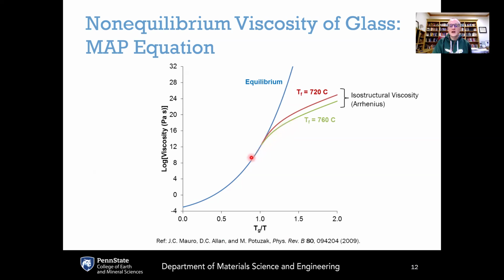You can see how the curvature here is changing gradually as the supercooled liquid departs from the blue line. It goes through this curved region, through this glass transition region, and then gradually freezes into this straight line behavior where the scaling is Arrhenius. And only at that point is the viscosity strictly isostructural. Now, depending upon how fast or how slowly you cool the supercooled liquid, you can freeze in the structure of the glass at different points. And those points where you freeze in the glass structure can be given by the so-called fictive temperature, TF.